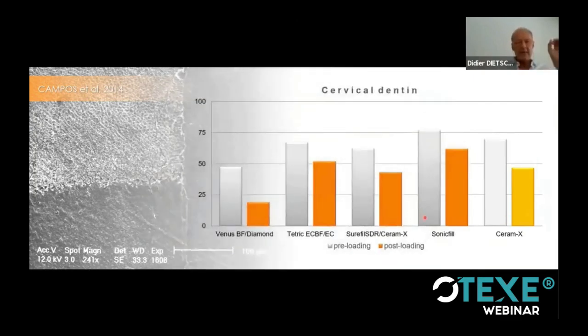If we go to cervical dentin, you need to look, by the way, at the orange bars. I think you realize that. So this is the post-loading condition. You see that none of the products but SonicFill provided adaptation above 50%. Only SonicFill provided adaptation above 50%. We're in the range of 60%, 63%, if I remember well the exact data, which is not the worst result we ever had with bulk filling material, but we are still relatively far from the 74, 78% of classical layering with conventional composite material.